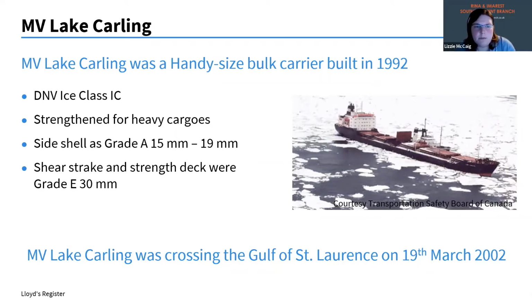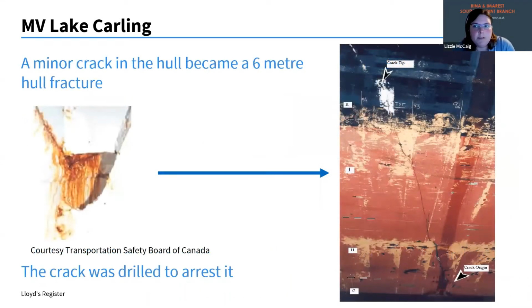She had grade A side shell, but the shear strake and strength deck were grade E. And all the steel grades did comply with the class rules at the time. So from that perspective, she complied with the rules. There was a minor crack in the hull and it turned into a 6-meter hull fracture. The crack initiated at the base of the web frame at frame 91 on the port side. They did find similar cracks at other locations. And the calculations carried out showed that the original crack was as short as 10 centimeters.